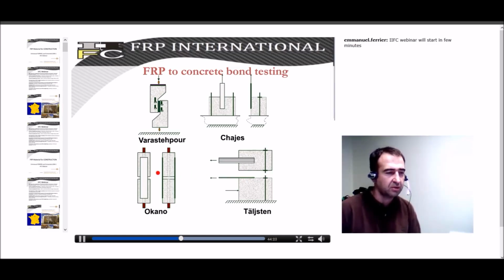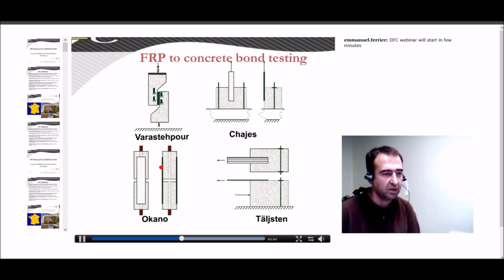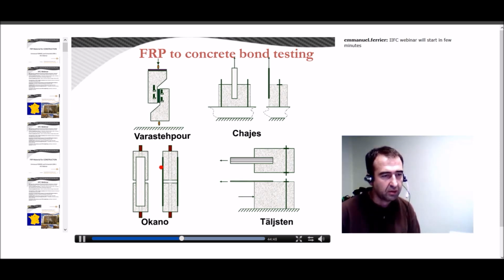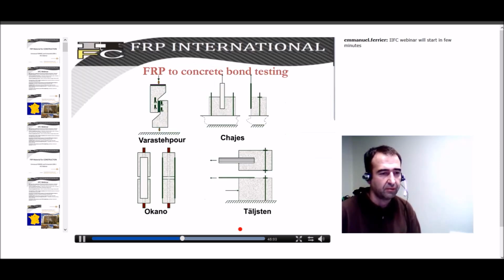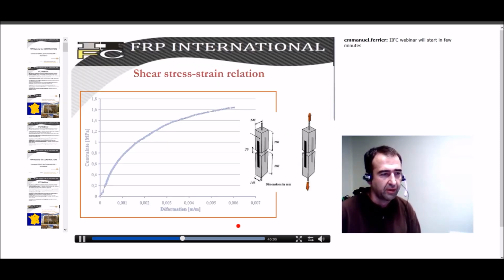Another common test is the double lap shear test. Two concrete blocks are connected by FRP material. Then the tensile stress is applied onto the concrete, and due to the tensile force developed in the FRP, you will have shear developing in the interface. The first author that used this test was Okano in 1995. It's quite a long time ago, and this kind of test has been fully used by other authors.